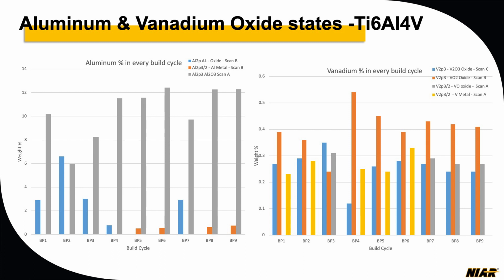But again, we are seeing multiple states of vanadium. Vanadium metal, initially some of them, the yellow bars, up to build cycle 6, we were able to see it. But after build cycle 7, we are not even able to see the vanadium metal at all. So any vanadium that we have seen is all in oxide layers.